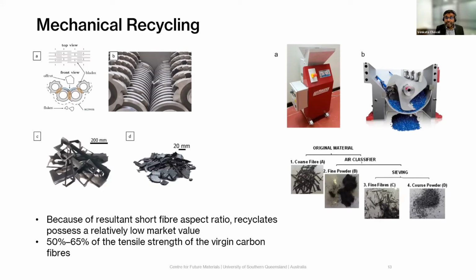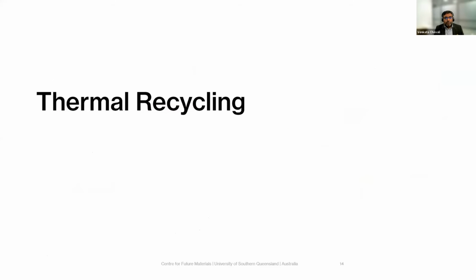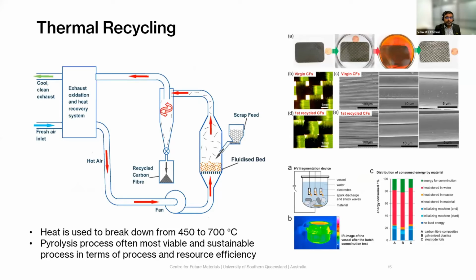And if you're looking again at thermosets, you're looking at almost continuous fibers. But in general, what you would see is that the fiber aspect ratio is quite short for the mechanical recyclate. However, 50 to 65% of the tensile strength of the virgin fiber from where this composite was made is actually retained. So if you look at thermal processes and how they weigh against the mechanical process, the major difference